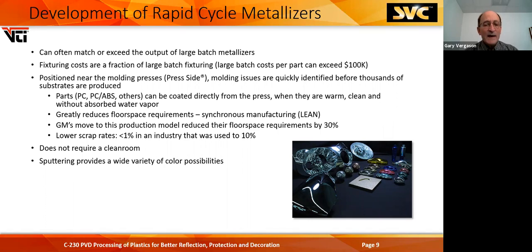Polycarbonate, PC/ABS and other resins can be directly coated from the press without a paint base coat. And that's when they're the cleanest they're ever going to be. They're warm and they do not have water vapor in them. Greatly reduces the floor space.